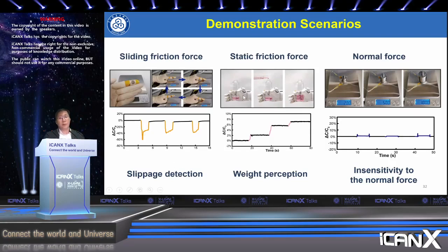And we also put it on the robot hand. There's no movement. So when we put water in the bottles, we can see that the static friction force increases, which is good for weight perception. And when we put the weight on top vertically on our device, we can see that there's negligible sensitivity to the normal force.